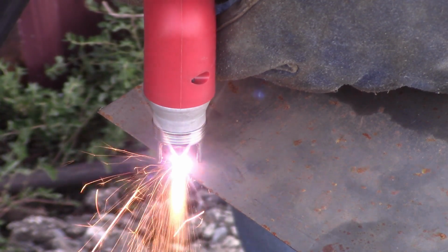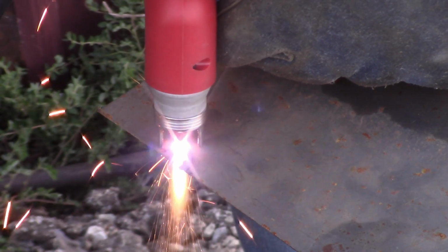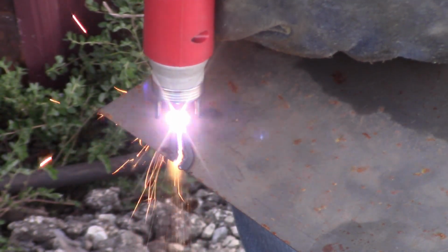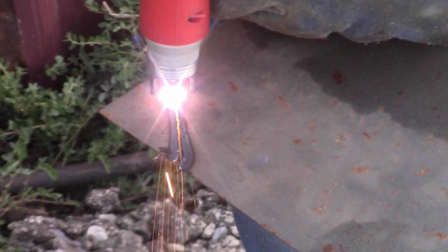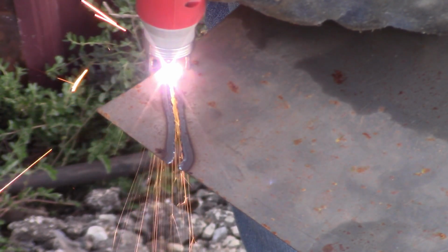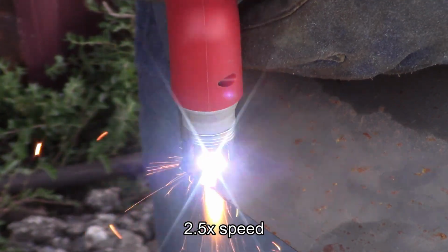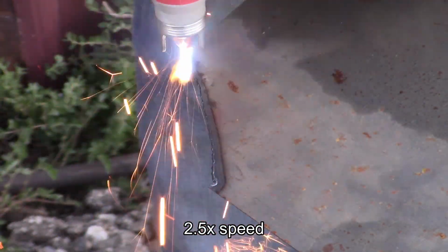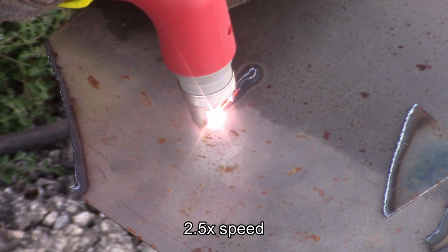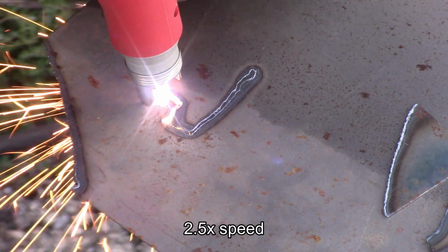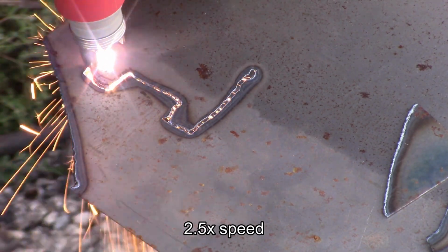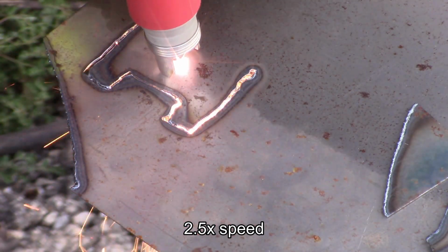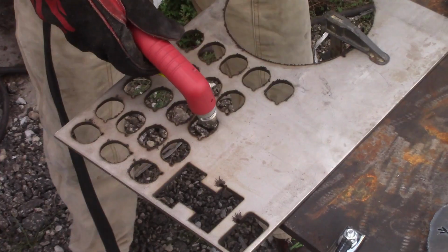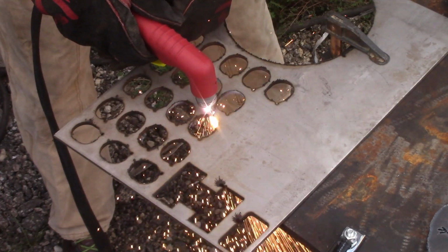The thinnest material I cut was 30 gauge sheet steel, which is around 12/1000ths of an inch or 0.3 millimeters thick. This was way outside the range on the chart, and the torch was really just too hot for something this thin, even at the lowest amperage. It cut through just fine, and the arc never went out, but there was just a melted globular edge left over. It did great in stainless steel.